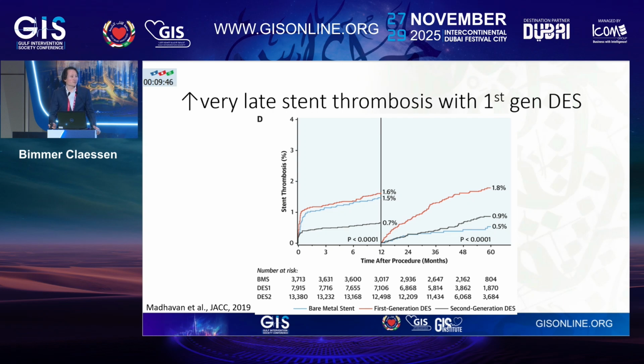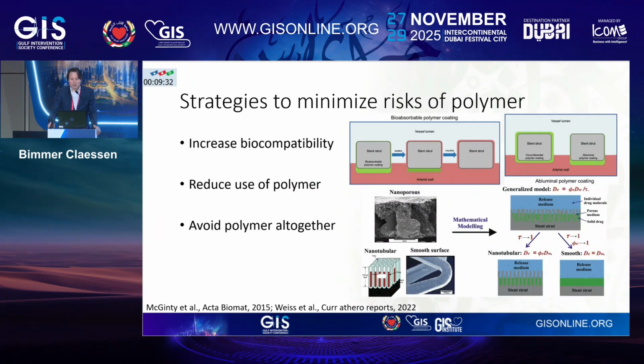And that's indeed what we saw with these first-generation drug-eluting stents, that there is a significant increase in stent thrombosis, particularly very late stent thrombosis, compared to bare metal stents and compared to second-generation drug-eluting stents. So there are a couple of strategies that were then used to minimize the risks of the polymer. And those include the using of increased biocompatibility. The first generation drug-eluting stents used polymers that were not biocompatible, but second generation drug-eluting stents used fluoropolymers. And the fluoropolymer is something like a non-stick coating on your pan. It hardly interacts with any other molecules, and it doesn't cause for any allergic reactions as the first generation polymers may do.